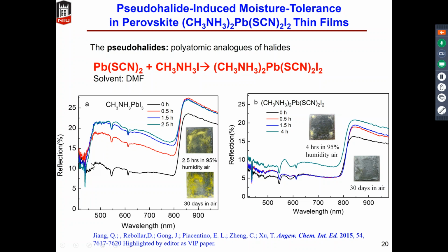And this is the reflection spectrum of the films at different times. However, this thiocyanate-based, pseudo-halide-based perovskite seems quite stable under humid air. As you can see, even after 4 hours in 95% humidity, the color still remains black in the center, and some part of it becomes white. But after 30 days in lab air, it still remains black. So this is quite exciting.